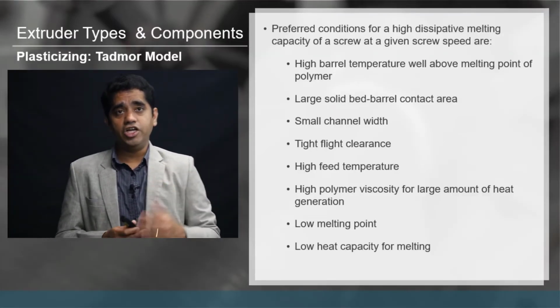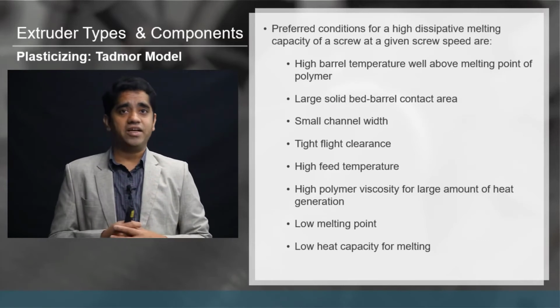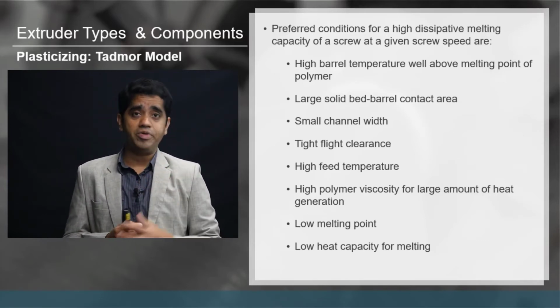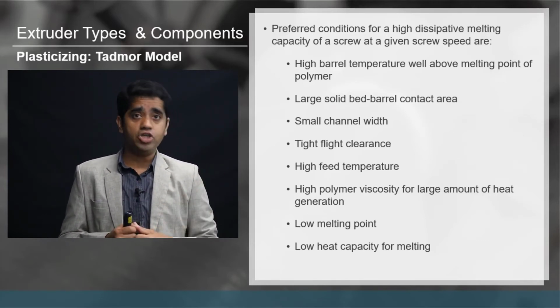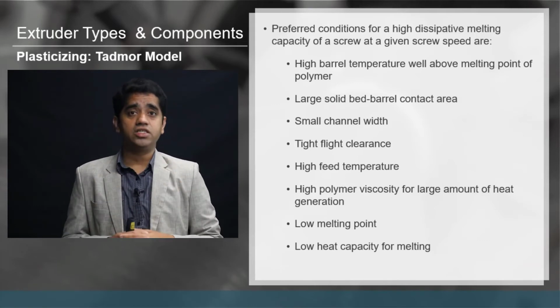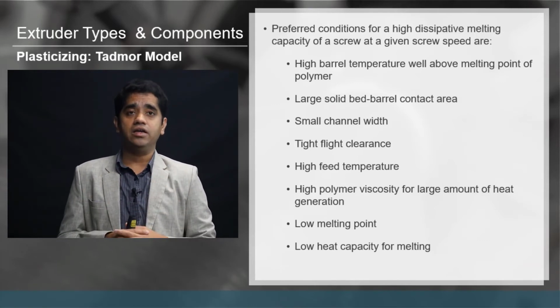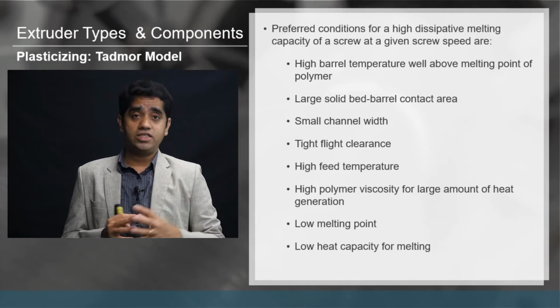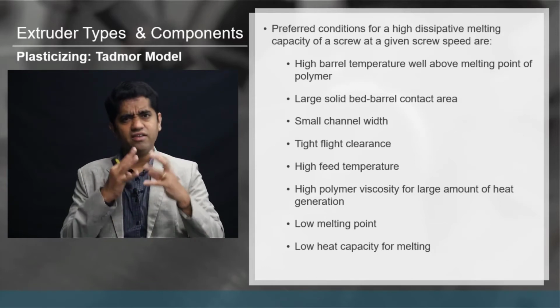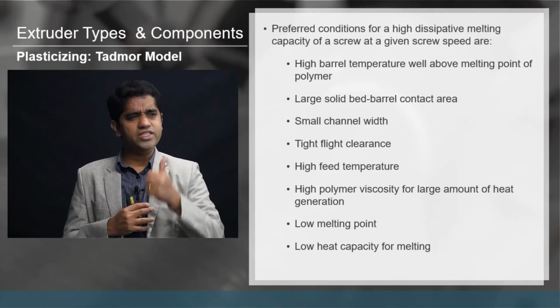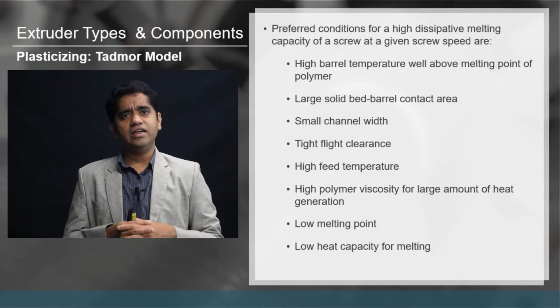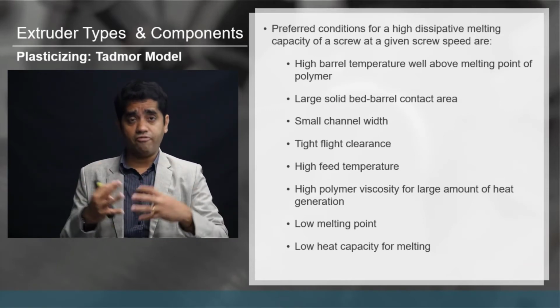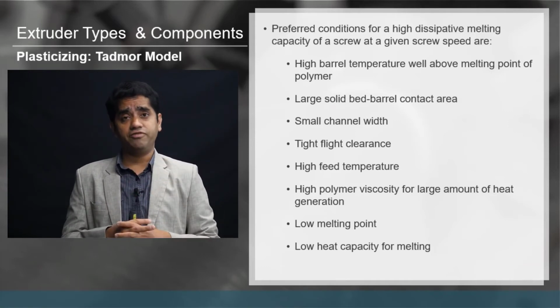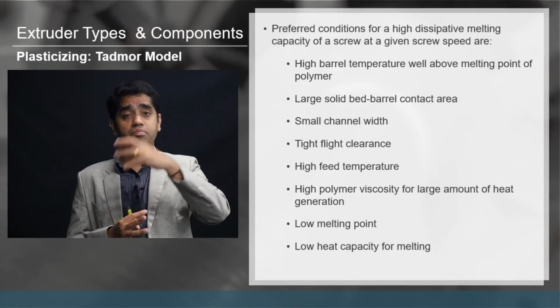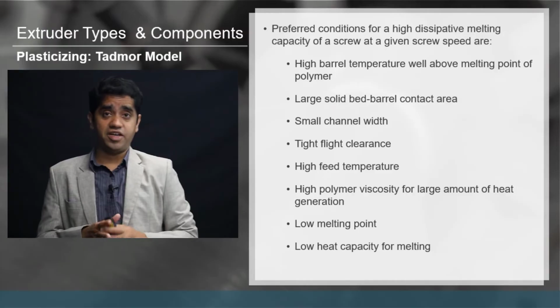Some of the preferred conditions for a high dissipative melt capacity of a screw at a given screw speed could be high barrel temperature or smaller channel widths. That also could help in expediting this whole system, and very tight flight clearances, because all of these will increase the shear heating that eventually will help to melt the solid beds more profoundly and much faster, so that the melt pool can be generated at a faster rate.